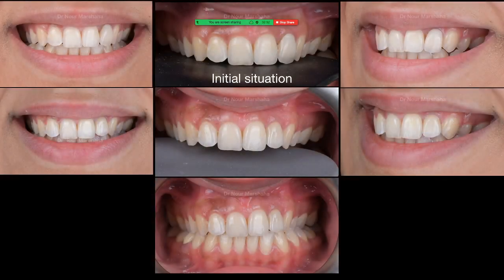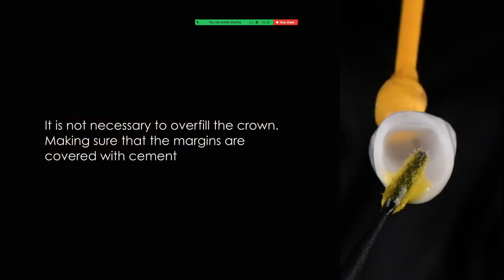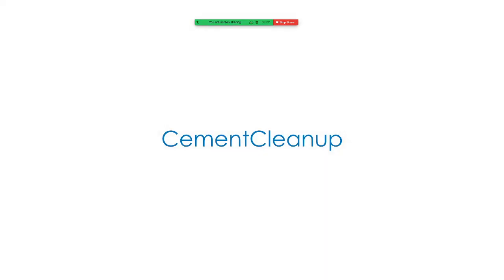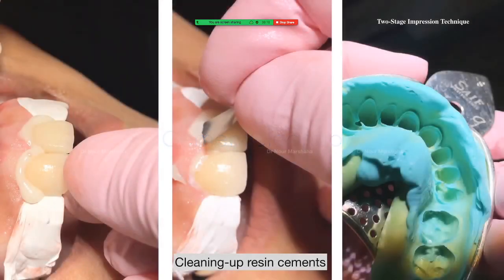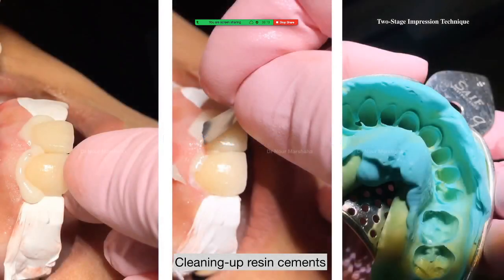And another case, this is before and this is after, we can see how it's going to be finally. Color shifts, we know that resins that contain tertiary amine and benzoyl peroxide, self-cured and dual cured, tend to darken with time. Okay, that's why we use light curing cement for veneers, not dual cure.